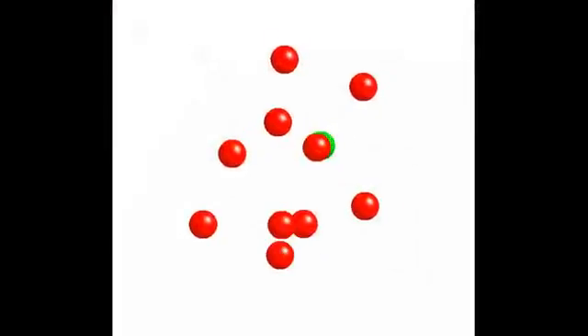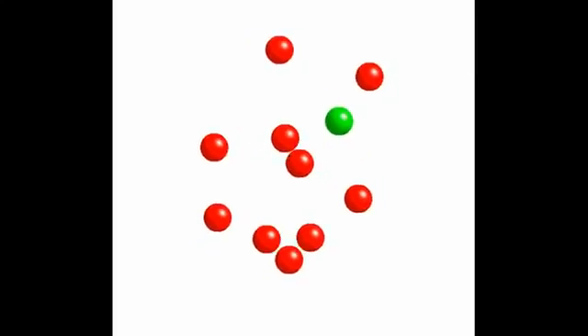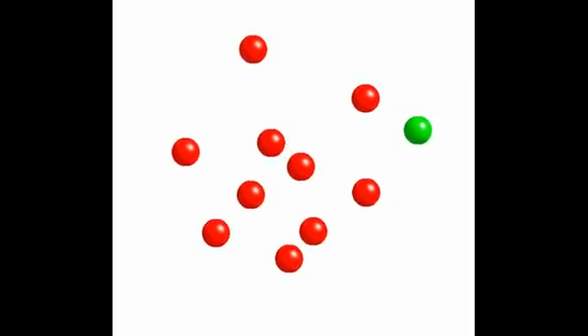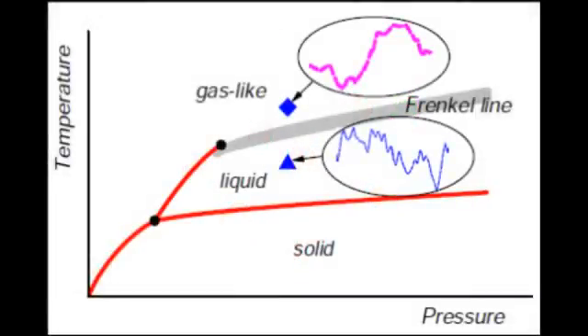The dynamics of a liquid near the melting curve, on the other hand, involve both oscillations and jumps to the nearest atomic cage. The relative contributions of the two types of particle motion in a liquid change depending on the temperature and pressure. If the oscillatory part in the liquid dynamics disappears, the system reaches the Frenkel line and transforms to gas-like state.